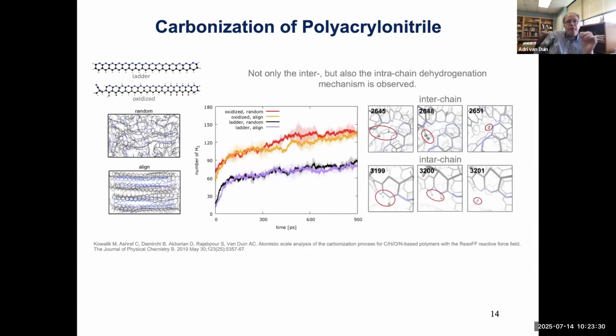Here's an example of the type of simulation we can fairly easily do. That is polyacrylonitrile, a very popular carbon fiber precursor. So this is essentially the structure. It has this very nice ladder structure where we have nitrogen atoms on the top and carbon at the bottom. Now, this structure by itself is actually very hard to carbonize. To carbonize it, you typically first have to oxidize it. And then the oxidized system, you can essentially take to high temperature and carbonize it.